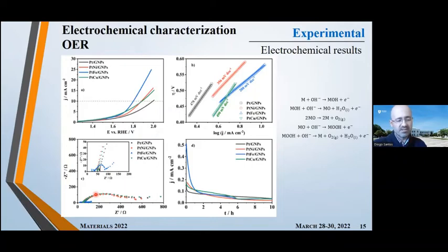We also did impedance spectroscopy, and impedance spectroscopy showed us that the resistance was much lower for the one with platinum iron compared to the other materials. So you see here the much lower resistance for the charge transfer reaction compared to the other materials. In terms of stability, they all show relatively similar stability.